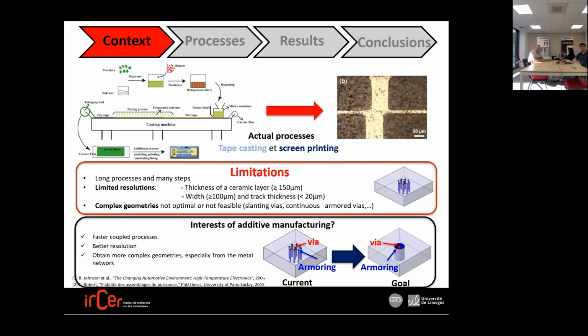This actual process has many limitations, such as, for example, a long process with many steps. We are limited in resolution. We can do ceramic layers with a thickness higher than 150 microns, and the width of the tracks must be higher than 100 microns, and the track thickness must be lower than 20 microns. Okay. In the same way, it's very difficult to obtain complex geometries such as armored vias or inclined vias, something like this. So what can be the interest of additive manufacturing? The first one is that it's a faster coupled process.